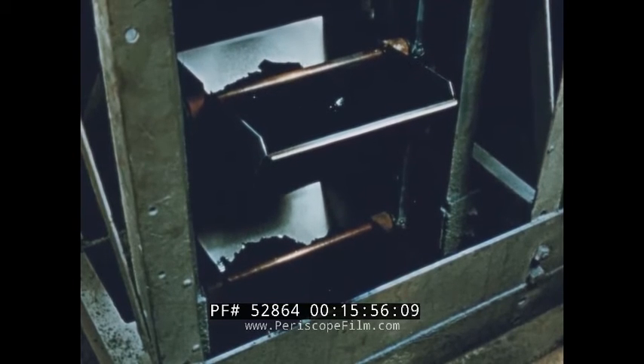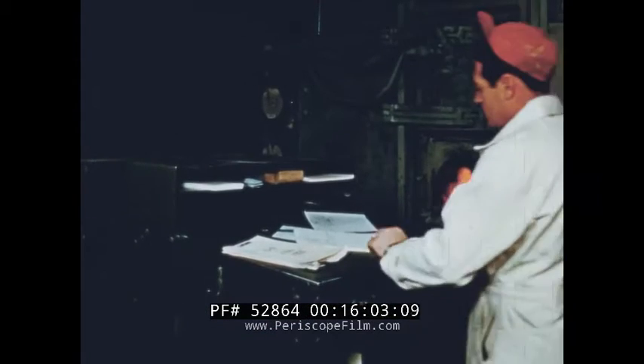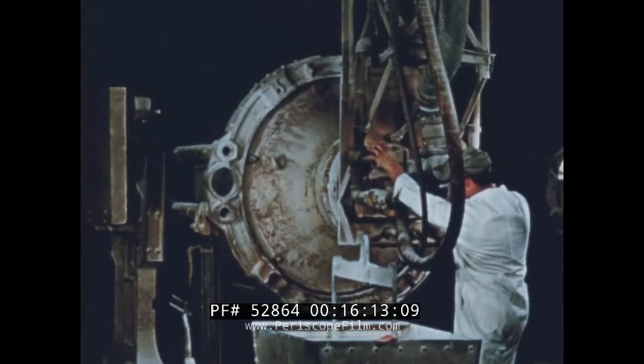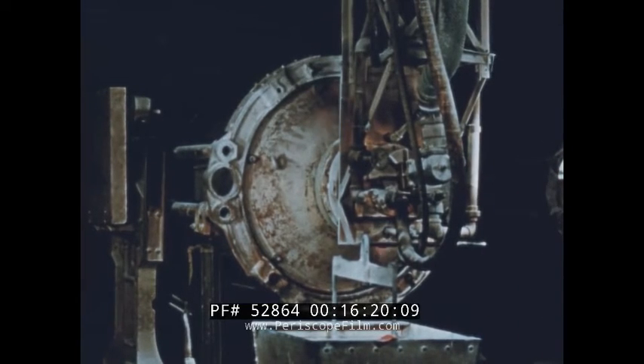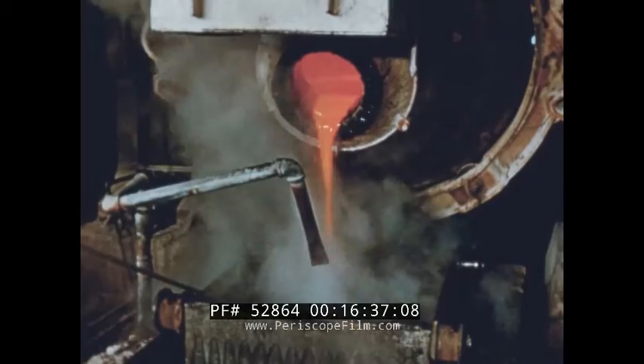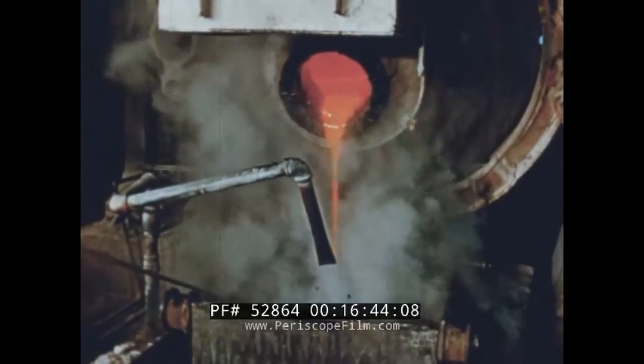You've seen white frit and clear frit — this is ground coat frit from the smelter. A complete record is maintained on each smelt, covering gas consumption, time required, charger speed, temperature, and the weight of batch tanks. Pemco's consumption of gas is enough to handle the cooking requirements for a city the size of Knoxville, Tennessee or Tampa, Florida for an entire year. The muffled roar of the rotary smelters — those controlled mechanical volcanoes of the industry — is like a squadron of jet airplanes warming up. When the batch is ready for pouring, the operator lowers the smelter slowly, and from a slight trickle the molten glass turns into a steady stream, which falls into cooling water. The change of temperature shatters the liquid into many tiny particles.